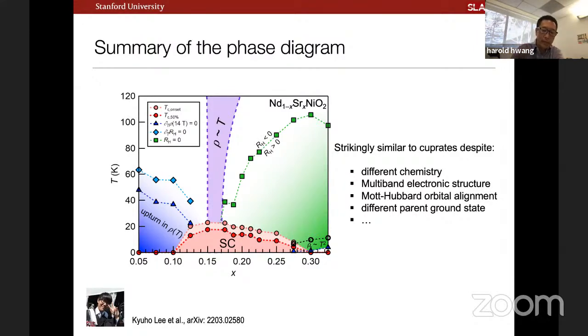And for example, in high field magnetic field studies to suppress superconductivity, it has a similar kind of phenomenology. We find a narrow band of T-linear resistivity near the peak of the dome, and then something that looks like it's headed towards a more conventional Fermi liquid on the overdoped side. As I mentioned, this upturn in resistivity tracks this maximum or change in the Hall coefficient and the sign change.